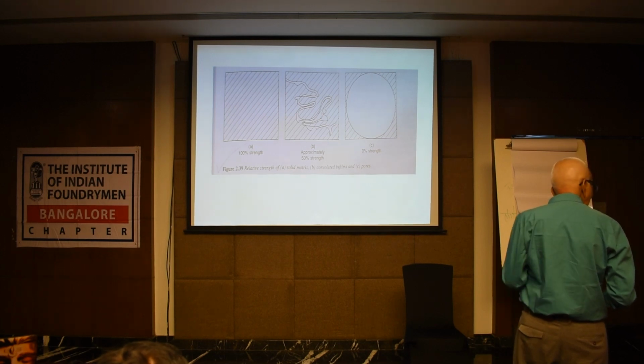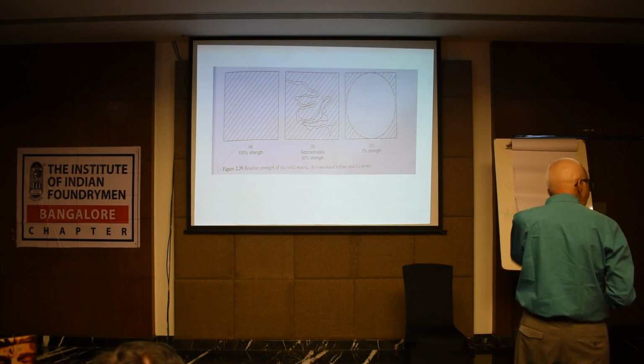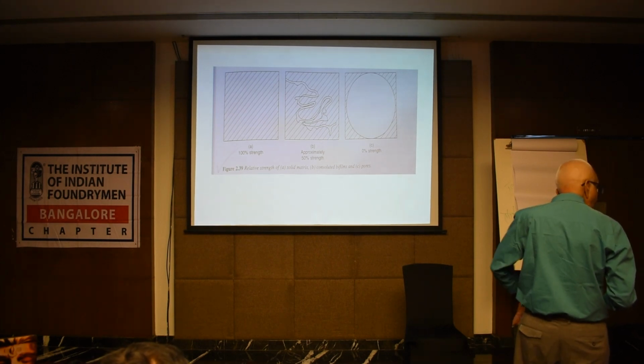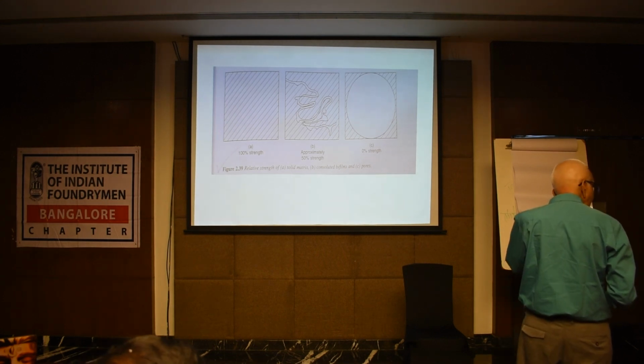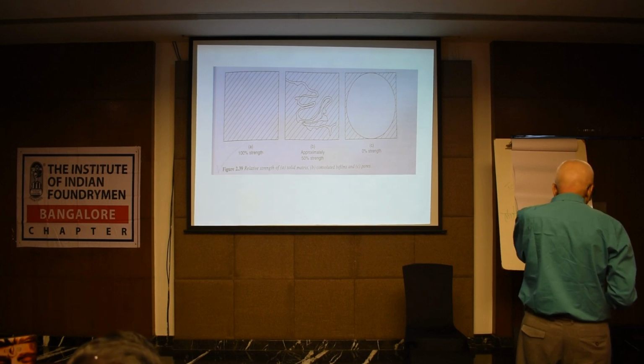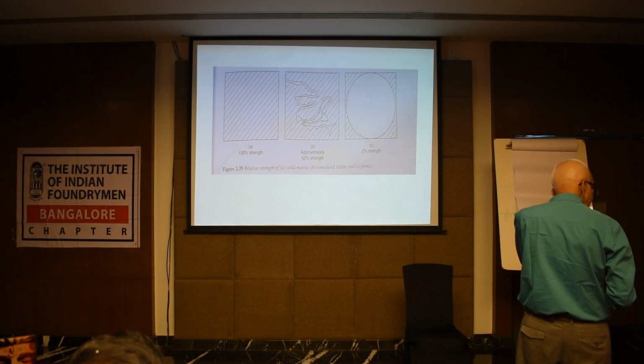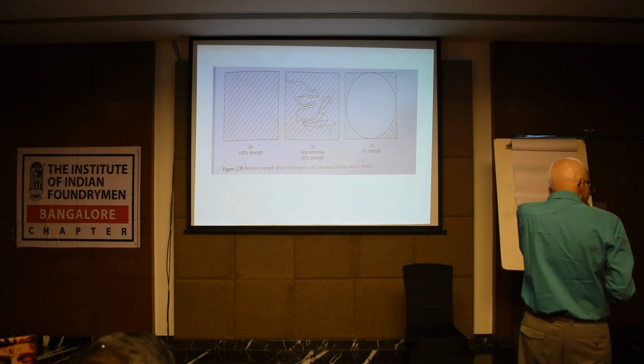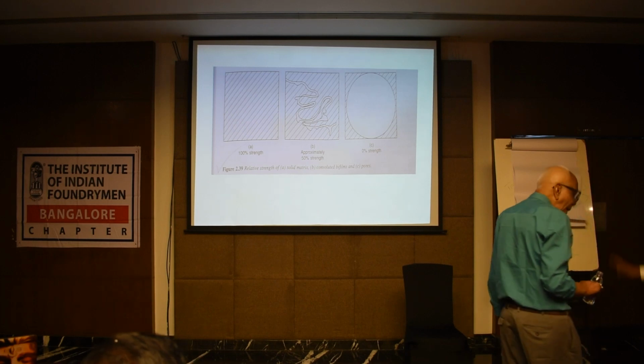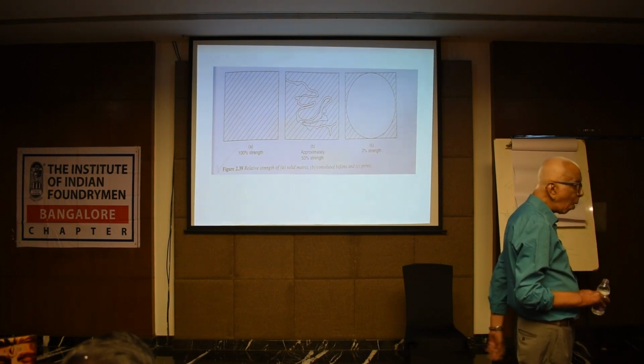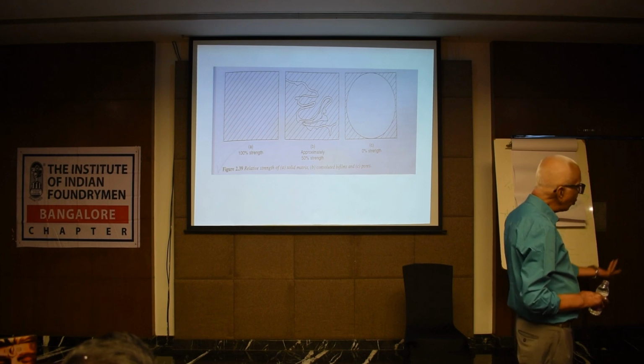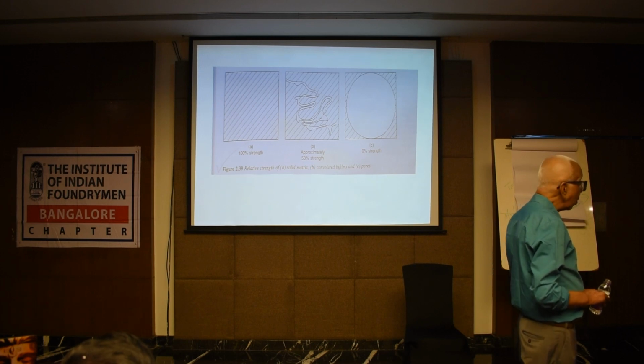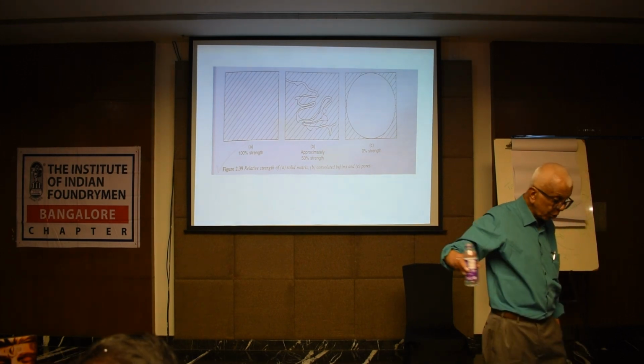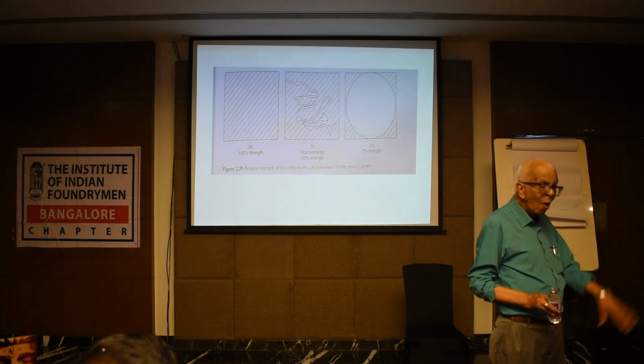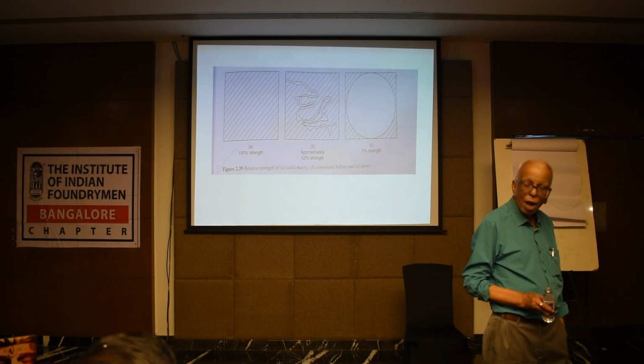If you have a pressurized system, bifilms get introduced in the gating system. When you make a mold, you have a gate, a sprue, a runner, and an ingate. When turbulence is there, it forms bifilms. They get entrapped in the casting, so properties will drop. Strength is reduced. To avoid that, reduce turbulence. So you use an unpressurized system or inverted horn gates. That's what I put. But he pointed out a very interesting fact, that a lot of stuff was known before the knowledge of bifilms. Yes, I agree with you.